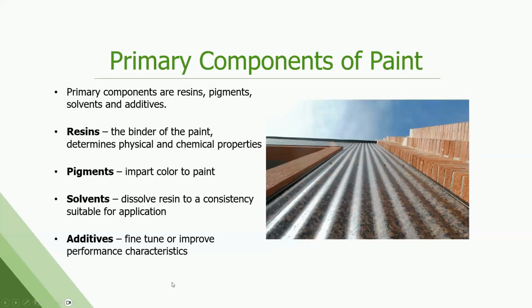In our world, for coil coating and for exterior roofing and wall, which is what we're focused on here today, the primary components are resins, pigments, solvents, and additives. The resin, also called the polymer, or the binder of the paint, really dictates the physical and chemical properties of that paint system. It's kind of carrying the bulk of the load on its shoulders. We then have pigments, obviously very important for color and aesthetics, but also important for some protection and weatherability as well, which we'll talk about later. Solvents, like I said, these are all solvent-based paints. They've got to be in a liquid consistency at a viscosity that we can pump it out of a drum onto a coater head on a paint line and apply it. You don't want it to be too thick, you don't want it to be too thin. And then there are additives, which just fine-tune the overall characteristics.